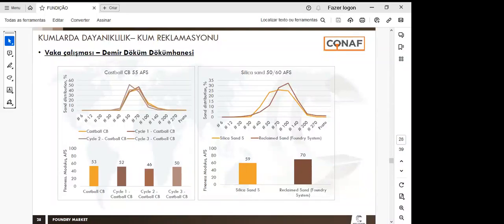We carried out some practical tests, okay, to validate the laboratory tests. In this case, we carried out the practical test in a gray cast iron foundry. And during the test, Castball was recovered by a mechanical process. And the sand distribution after 3 cycles was measured, okay? We can see the results.